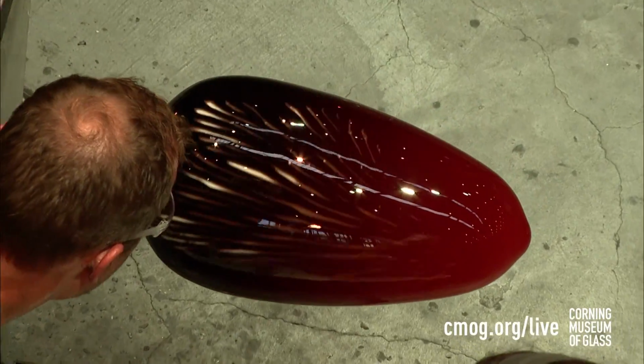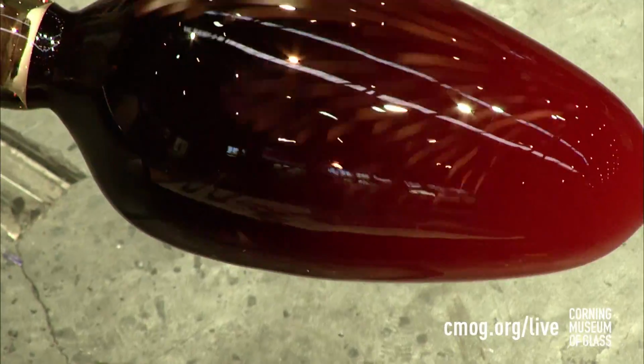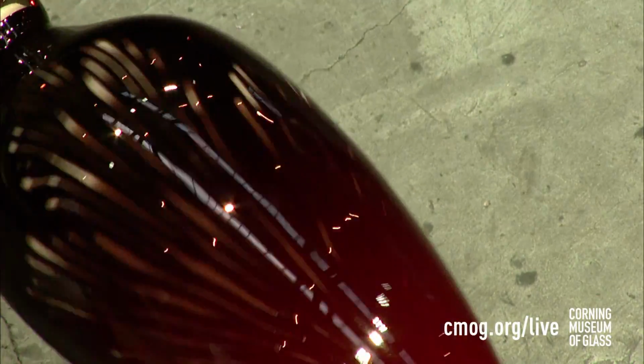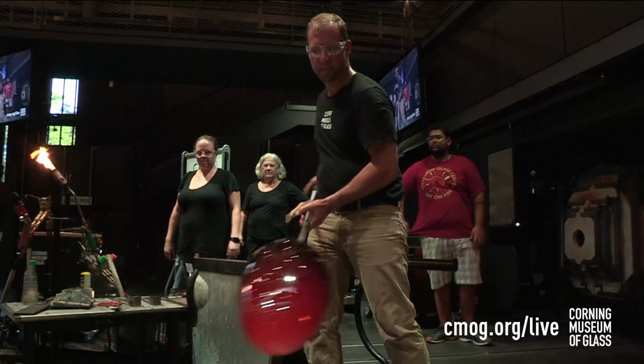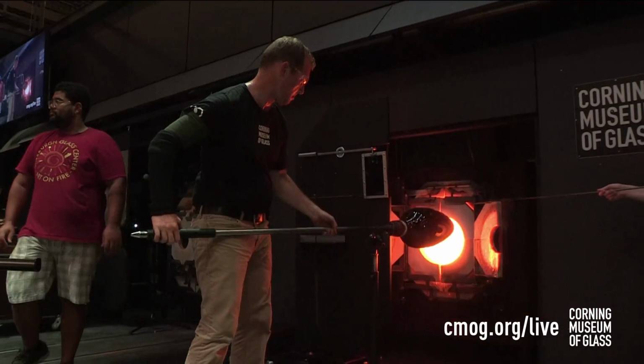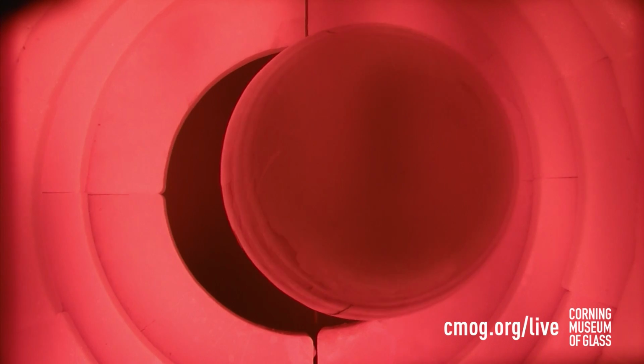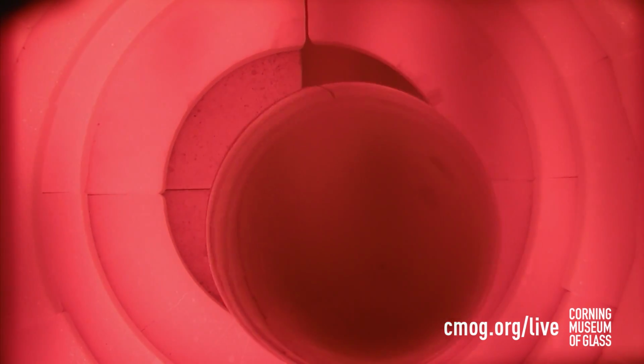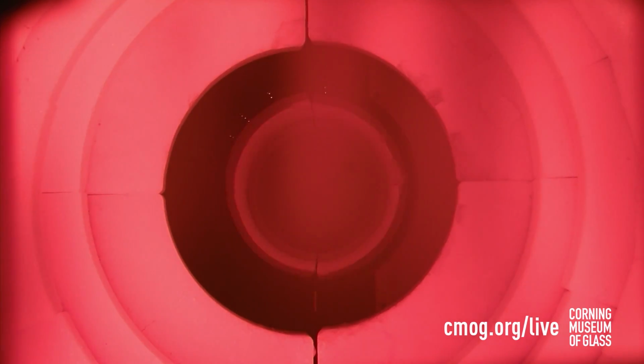Why doesn't it stick? It would. The newspaper ash would stick to the glass if it became dry. The newspaper is soaked in water, and I've actually had that happen before, so that's why I know that. If the newspaper becomes dry, if you keep using the paper or use the newspaper with a really hot gather right out of the furnace and it doesn't have enough water in it, it'll stick, and the ash will leave a little bit of a residue on the surface of the glass. But if we keep that newspaper soaked in water, it rides on a thin layer of steam and carbon, so the glass doesn't really even touch the newspaper. But it can, if you let it get too dry.